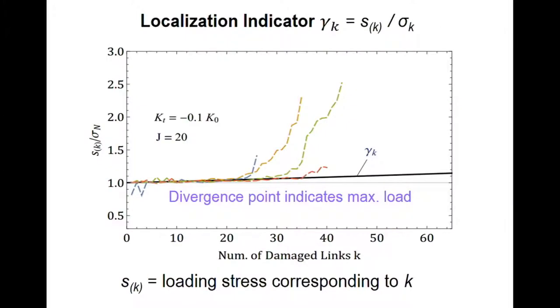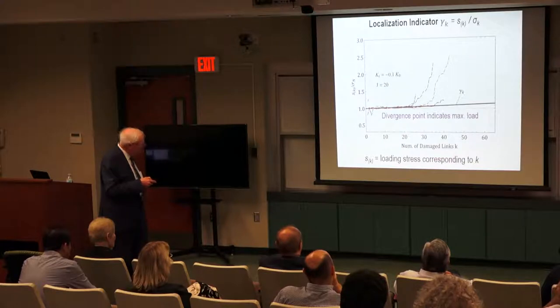Okay, eventually we looked at the nominal stress change with the number of damaged links. And at the beginning, it works, everything coincides, and suddenly they diverge. And we find that this divergence always corresponds to maximum load. So that tells you, in this case, that the number of jumps down, which gives maximum load, is 20. Not something else.